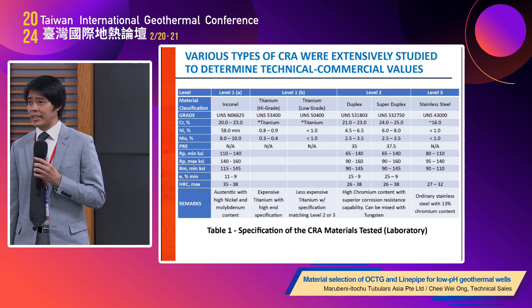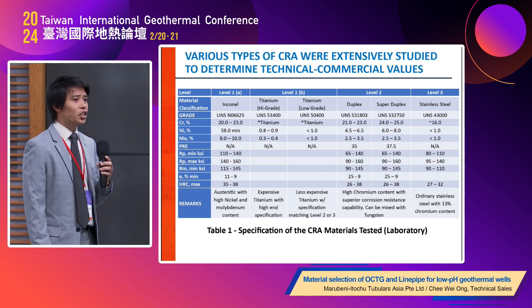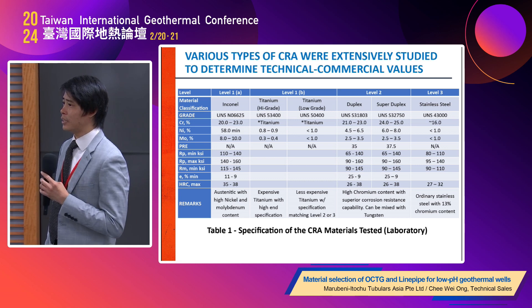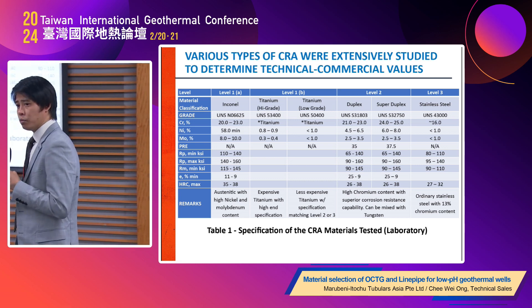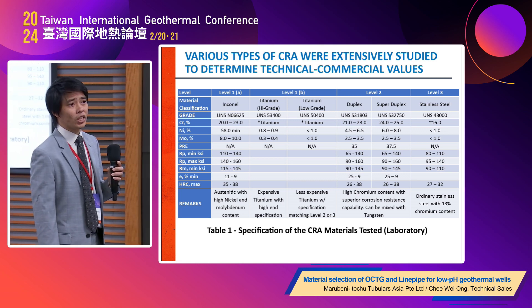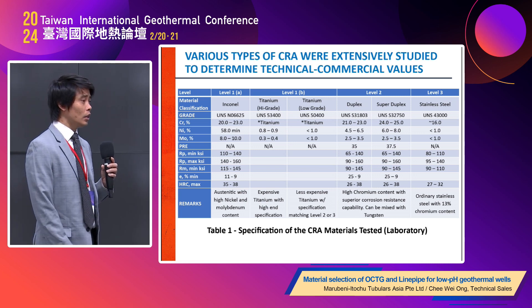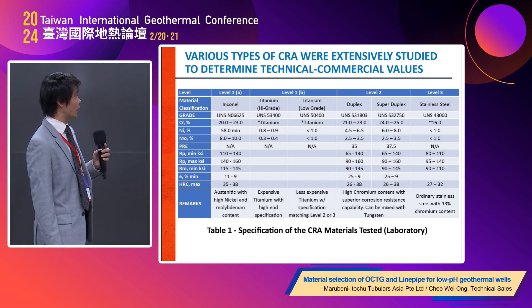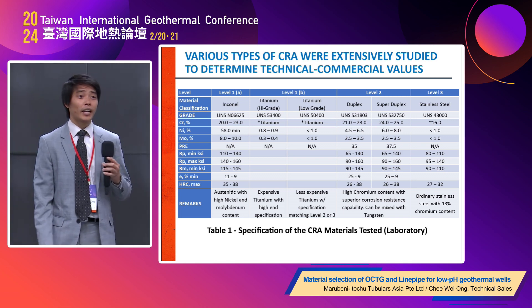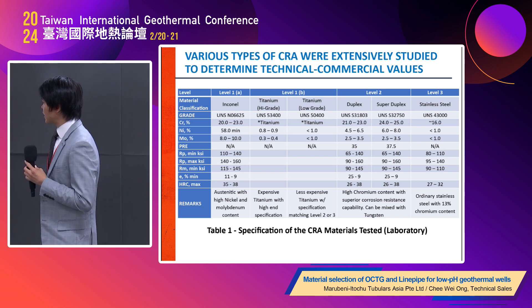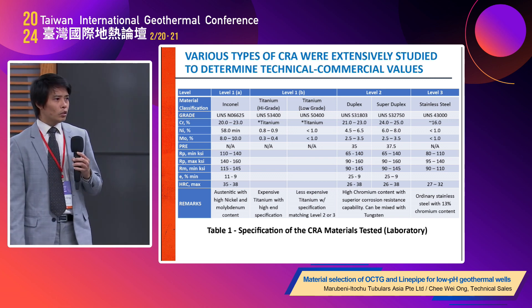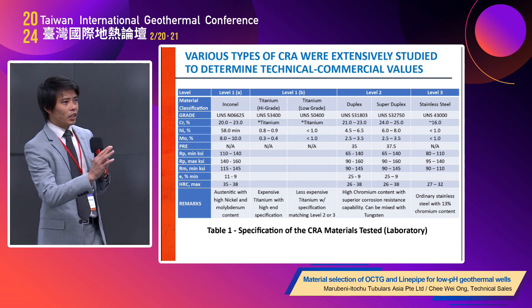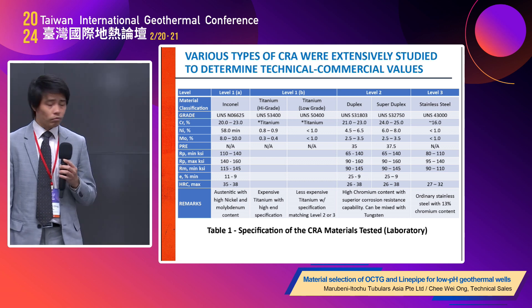We developed an extensive material selection chart in an initial study, breaking it into three categories. Level 3 covers martensitic stainless steel. Level 2 covers duplex and super duplex — commercially known as 22 or 25 chrome. Level 1B covers titanium material, and Level 1A is Inconel 625, an austenitic high-nickel alloy with molybdenum content. With this study, we found it was still too conservative and some proprietary grades were not considered, so we tried to identify potential candidates between Level 2 and 3.